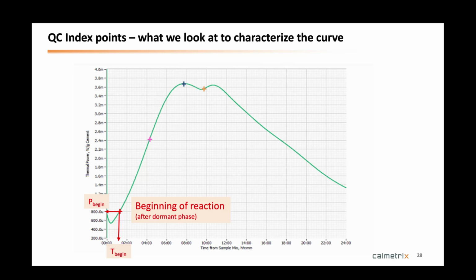You have the dormant phase where not much happens, and then all of a sudden it takes place. Like hydration starts, and it's like the beginning where it starts to work its way towards the initial set. So it's not quite initial set yet, but it works its way there. And by looking at the time when this happens, where the beginning of reaction happens, and the thermal power value at this point, we have here a consistency parameter where we can look how this varies over time. The second one is at the inflection point.